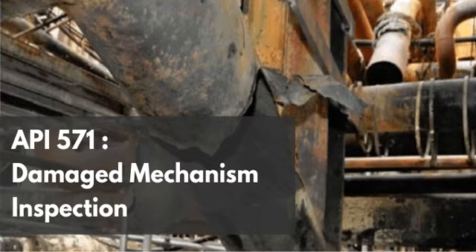Right. In a water-based system, oxygen helps form a stable, uniform, passive iron oxide film that protects the steel underneath. But in an anhydrous ammonia environment, the lack of water completely changes the electrochemistry. Because without the water, that protective rust layer just can't properly form. Exactly. You cannot form a stable passive film. So instead of protecting the steel, the trace oxygen acts as a potent cathodic depolarizer.